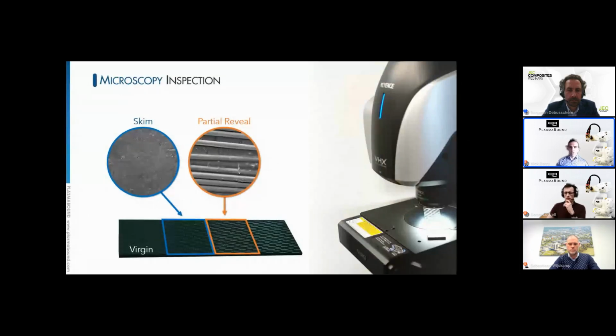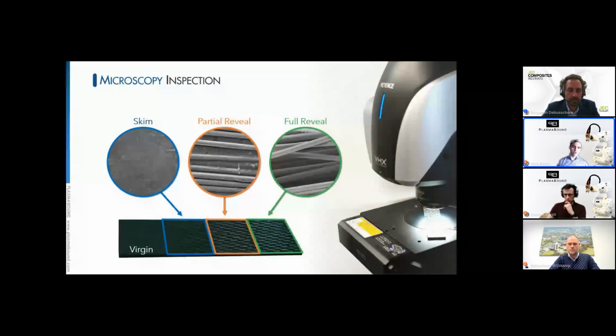Then finally is the full reveal. And this means that the fibers are fully exposed and no polymer is present around the fiber structure. But critical to all of these is that there is no fiber damage occurring during the treatment. They're only a successful treatment if the fiber has not been damaged. So depending on the customer's requirement, we could use any of these 3. There are levels or increments between them, obviously between skim to partial and partial to full reveal, but these will be the fundamental needs we would discuss with a customer. Sometimes the customer doesn't know what they need, but usually our engineers can work and support the customer in understanding what their needs or requirements are.